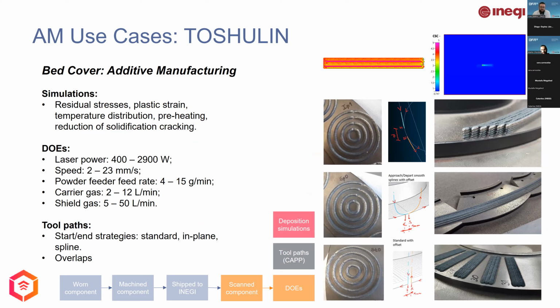To aid in the definition of the additive manufacturing process, a set of simulations was performed aiming to assess residual stresses, plastic strain, the need or not to preheat the part, and the occurrence of cracking in the part after the deposition process. With the help of these simulations, several experiments were performed with the material to be used in order to obtain a set of parameters that would guarantee good mechanical performance to the repaired part. The main hurdle that was overcome here was the prevalence of cracks in the deposited material.